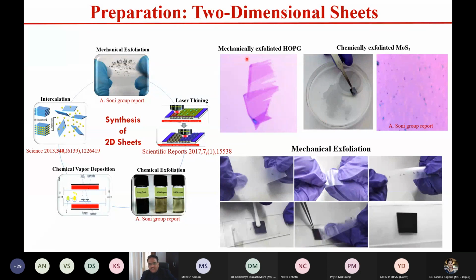So this is the image of mechanically exfoliated graphite, graphene. You can see there are different optical contrasts here, which shows there are different thicknesses of these layers. And again, this is a chemically exfoliated film, and this is the quality of the film here. So if you want large scale growth of the film, the solution methods are better.